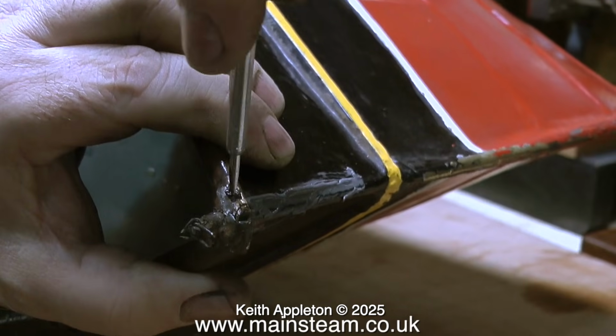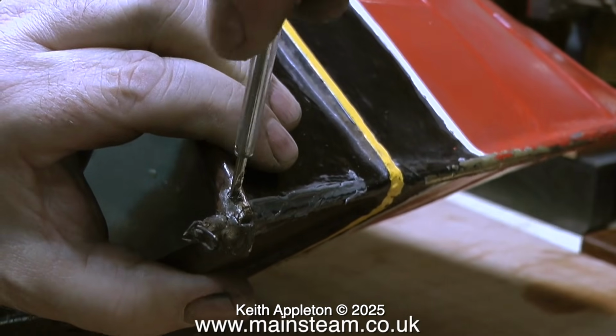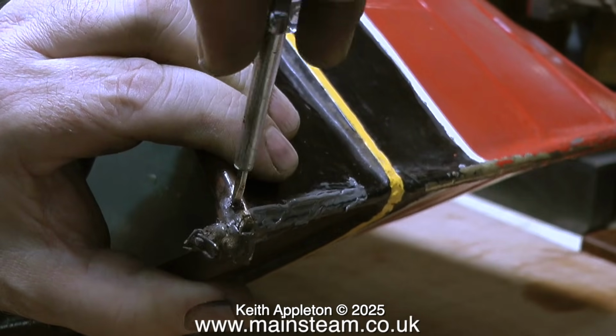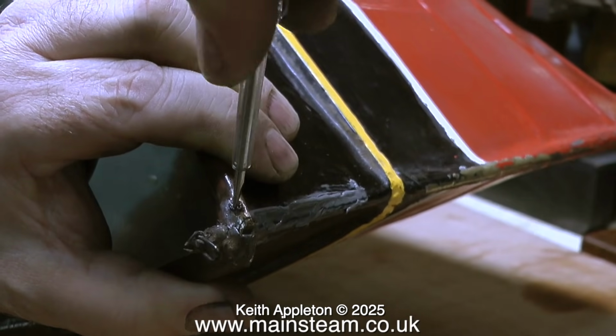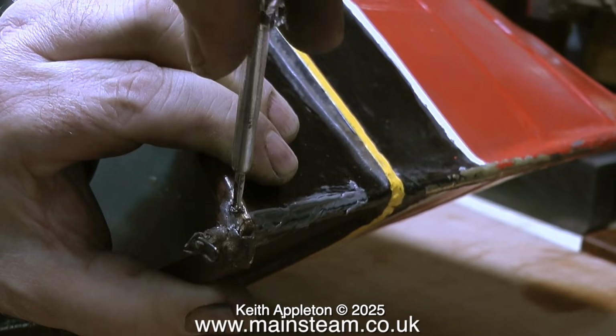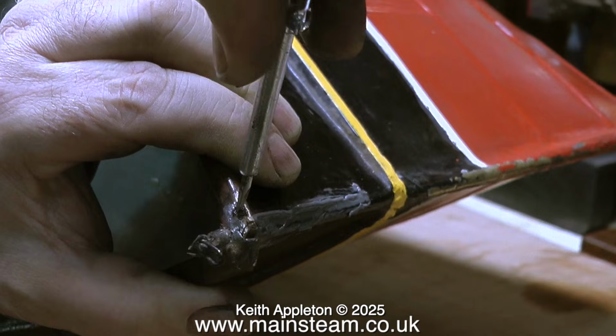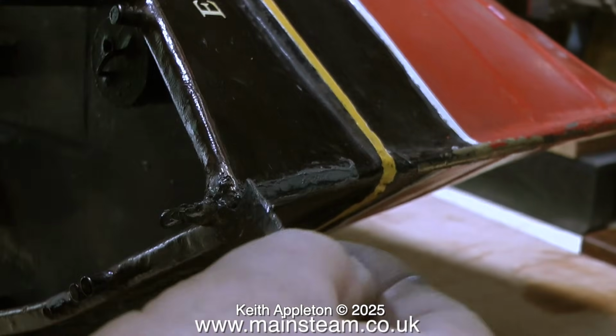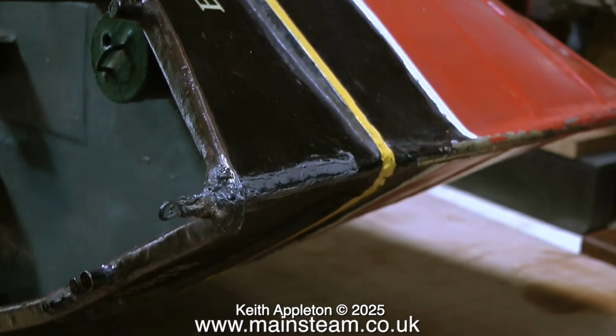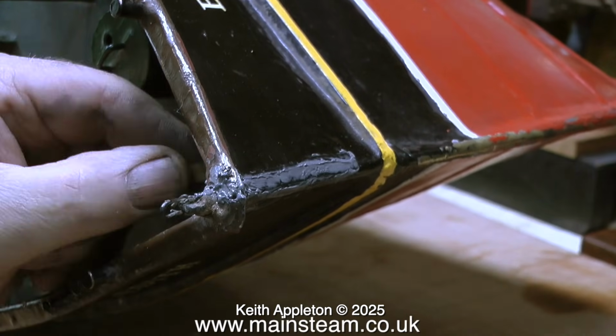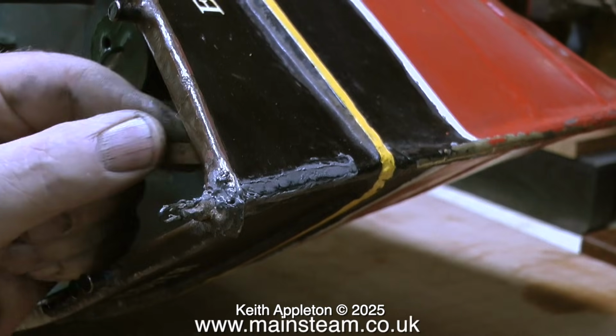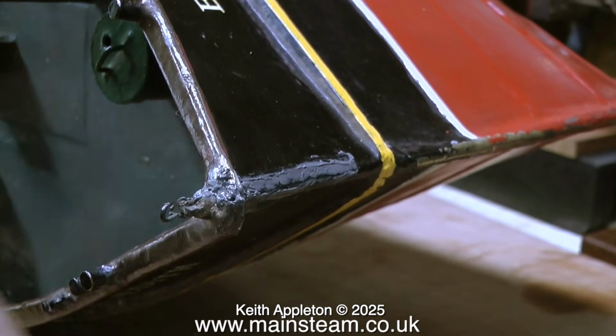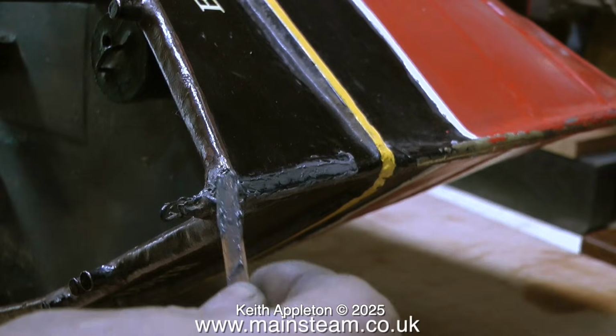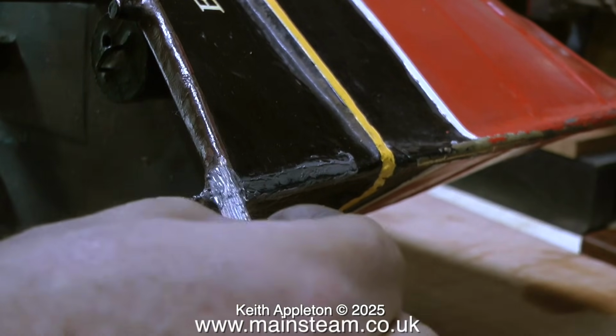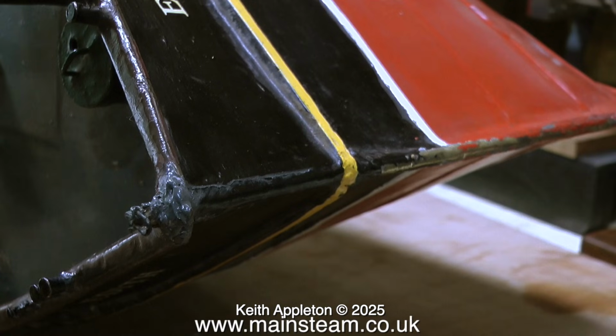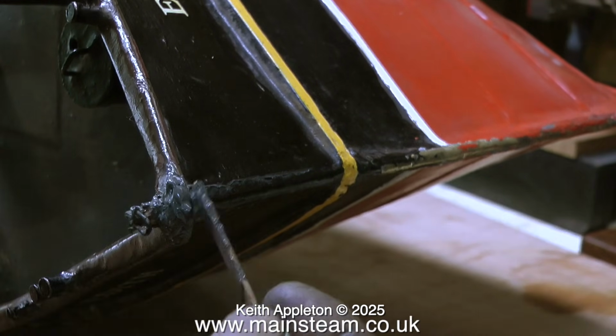In this clip, I'm screwing in the 8BA bolt, and it has to be quite tight to hold this part together. And because this small steel bolt is made of stainless steel, it's never going to rust, and it's much stronger than a brass bolt, so I can really tighten it up to nip these parts together. And once that's done, I can spend some time tidying up the amount of JB-Weld on the repair. Obviously, some JB-Weld squeezed out on the inside and squeezed out on the outside, so I'm removing the excess JB-Weld, but I'm not wasting it. I'm using it on the top of the combing to hide the bolt. And when this is all ground to shape and painted, only you and I will know that it's been repaired.